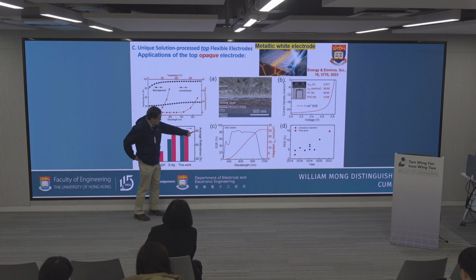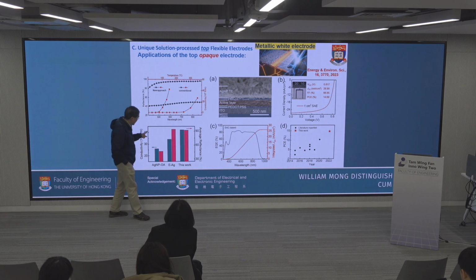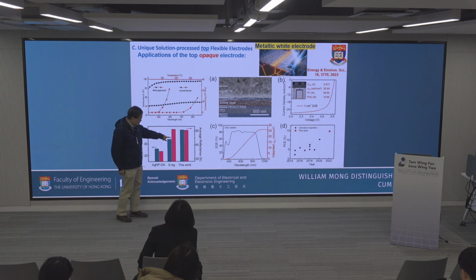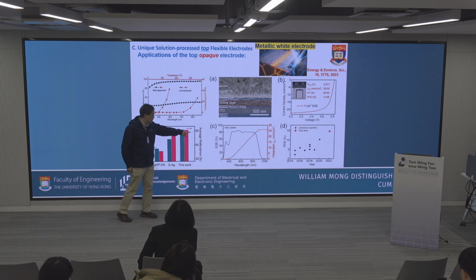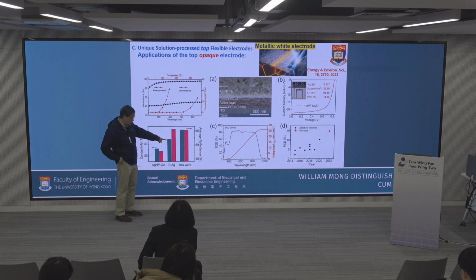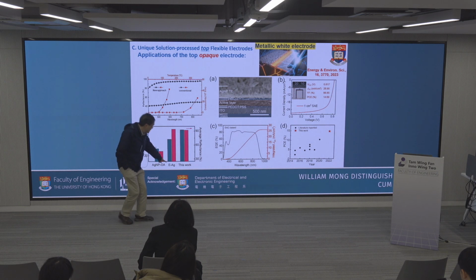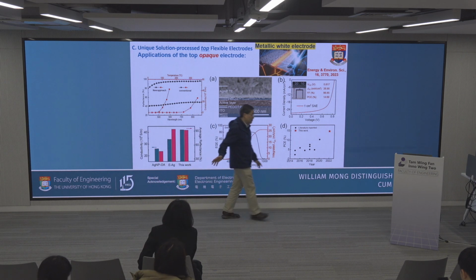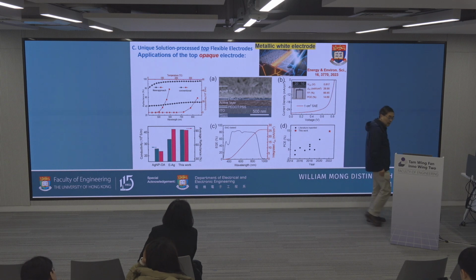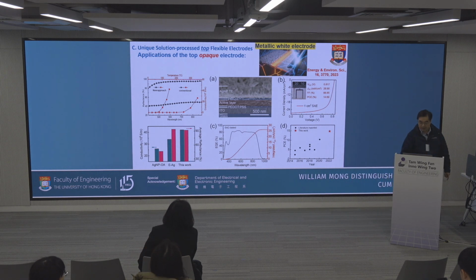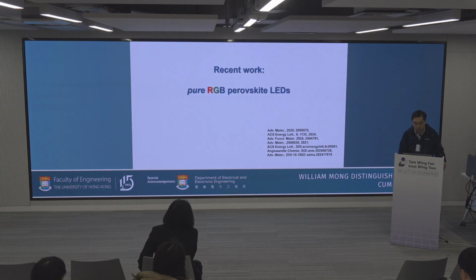Compared to the evaporated electrode, this is the solution process metallic white silver electrode. The reflection is more than 90%. The conductivity is pretty okay. The evaporated electrode has a good reflection, but we are about there, and we have even better conduction than the evaporated one, where E stands for evaporated. So we are pretty okay, and finally we make the OPV with reasonably good performance. So we make it all solution process.